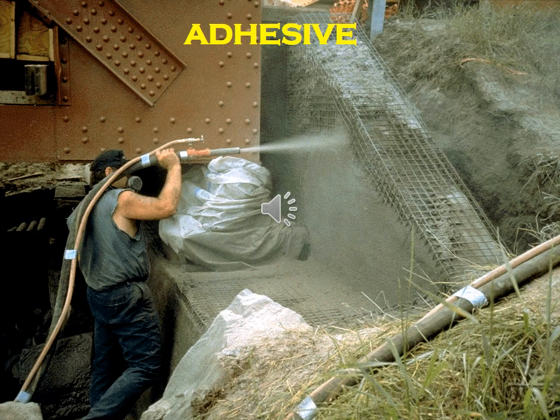This picture shows shotcrete, that is, concrete sprayed with a shotgun over a surface. This type of application is very common in tunnel linings and in areas where landsliding is to be resisted, in large areas, particularly say dam construction or powerhouse construction inside the mountains. This type of concrete, when sprayed over the surface, tends to fall down from that surface unless it has sticky properties. Micro-silica makes it sticky so that the rebound of concrete from the surface is low, so the usable concrete increases. If rebound is more, wastage is more.